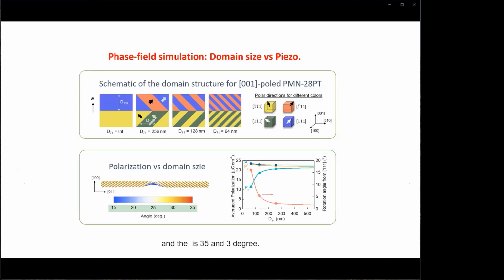35.3 degrees. However, the presence of 71-degree domain walls causes the polar vectors to rotate towards the 011 direction to minimize the polarization gradient energy and also elastic energy, as shown in this figure. With decreasing the domain size, the impact of the domain walls on the polarization becomes more prominent, resulting in a larger deviation of the polarization from the 111 direction.